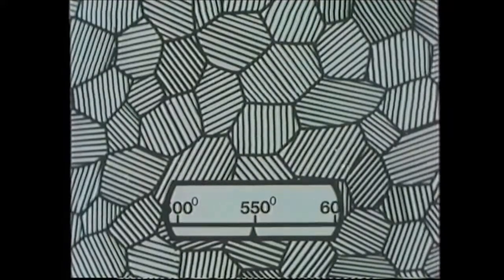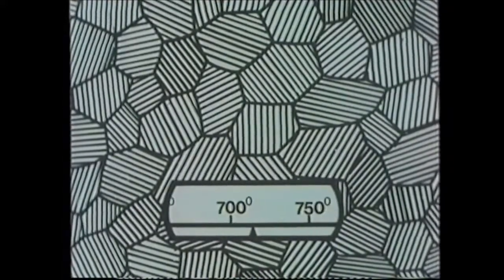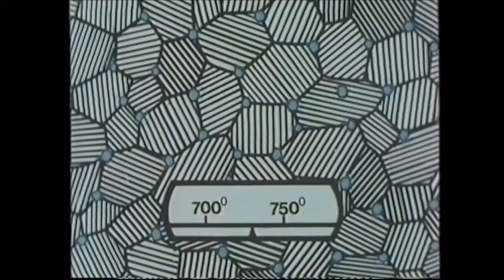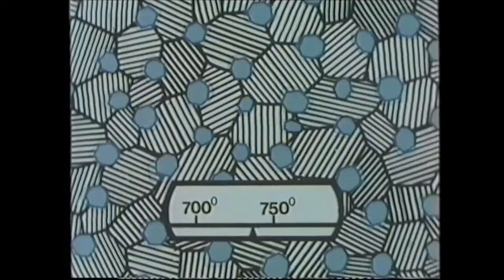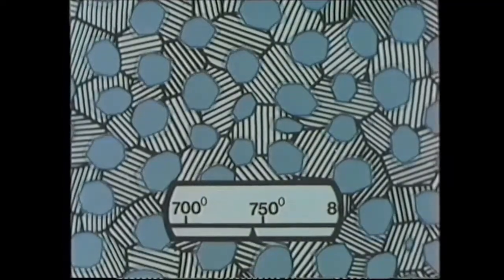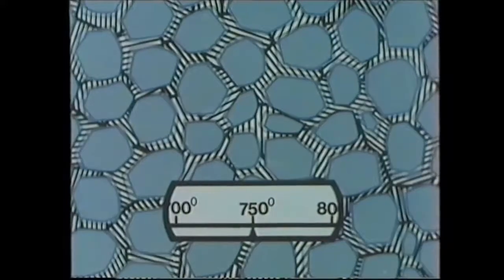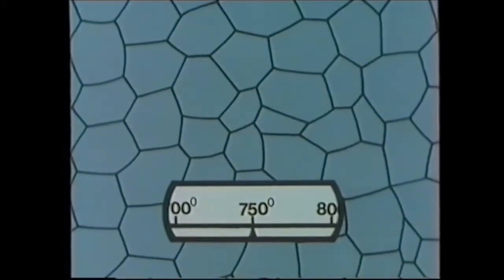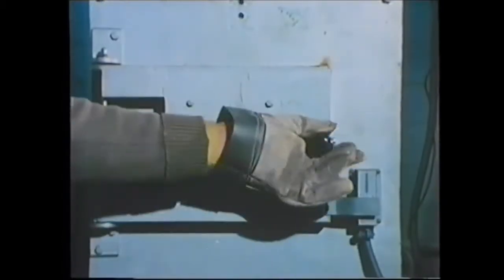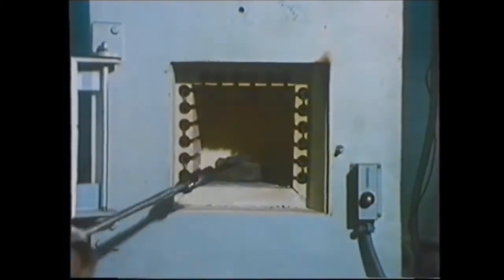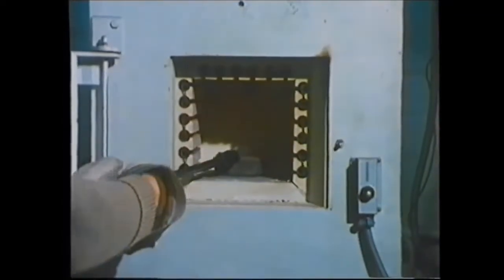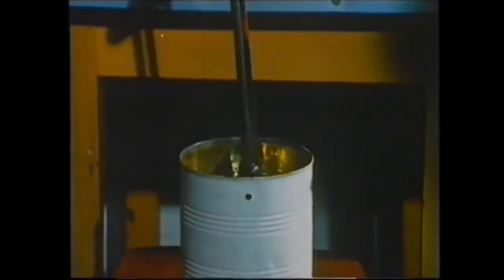Nothing happens until the temperature reaches about 720 degrees. Now, exactly the same thing happens here as it did in normalizing. New grains of a completely different structure grow out at the old grain boundaries. Right, now for the quench. As the temperature falls, in each new grain, a needle-like structure forms. This structure is very hard indeed. It's also brittle.